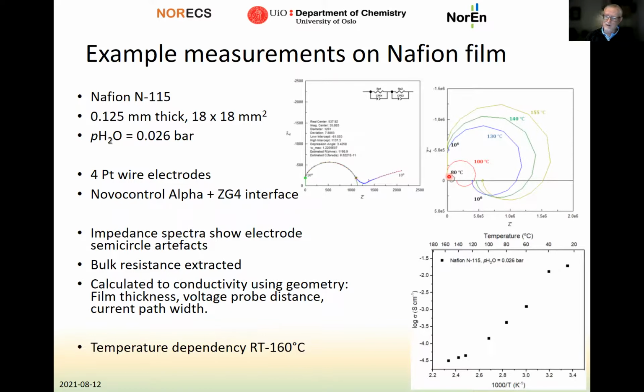And these can then be converted to conductivity by taking the geometry into account, that is, the film thickness, the distance between the voltage probes, and the current path width. Then we can calculate for different temperatures the conductivity of the film, going down with increasing temperature on this inverse scale, which is how polymers behave, because the relative humidity goes down when the temperature goes up, and the mobility of the charge carriers decreases. Here we measured up to 160 degrees on this head.